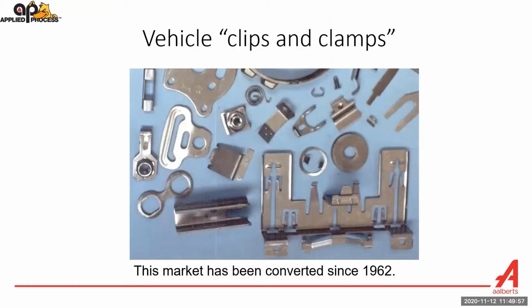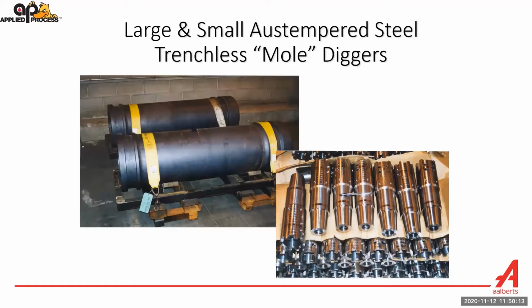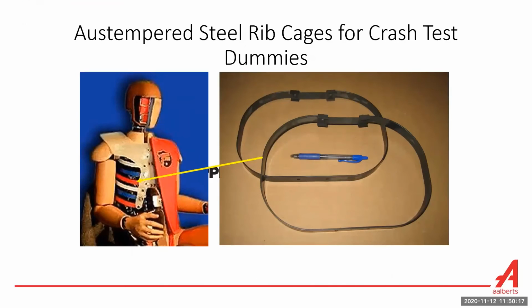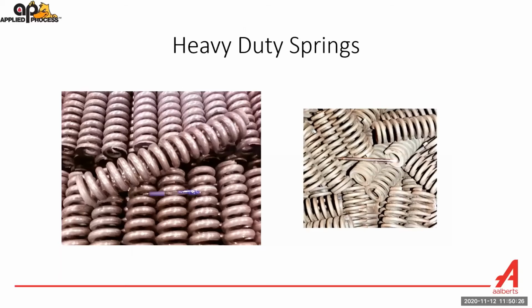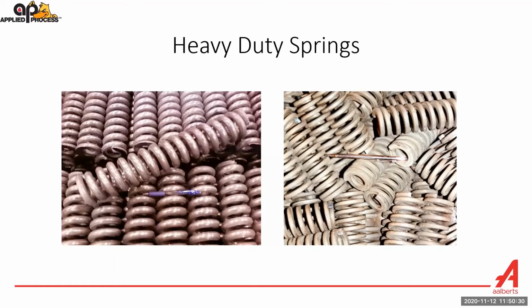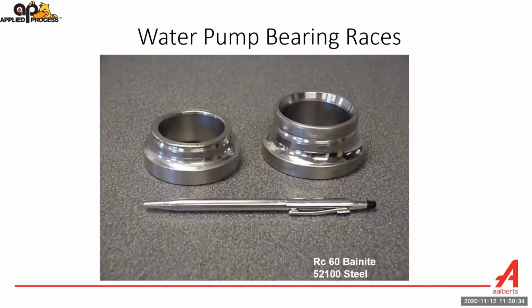So where is Austempered steel used? Most people actually come in contact with it every day in your vehicles. There's a lot of Austempered clips and clamps. Seatbelt components are oftentimes made with Austempered steel. Horizontal boring bits, seat brackets. Years ago, I don't know if this is still the case, the ribs in the crash test dummies used to be made out of 1080 steel that was Austempered. Heavy duty springs can be made out of Austempered steel. Water pump bearing races. We do a lot of work in the roller bearing industry, and we're talking about 52100 steels typically that have hardnesses in the range of Rockwell C 60, and very minimal distortion at the same time. So even in salt quenching, we can get to some extremely high hardness levels.